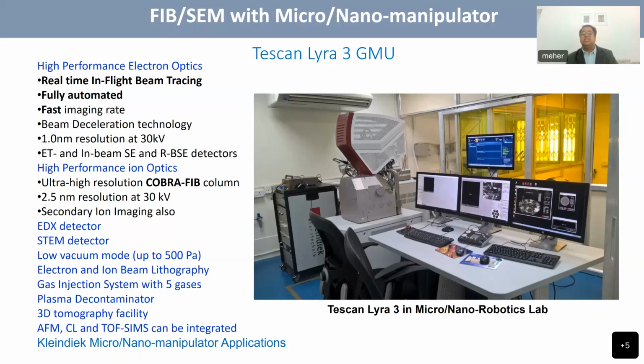because whenever we work with semiconducting nanoparticles, we use electrons for seeing those particles, and when we see the particles with the help of electrons, electrons also get deposited on the surface of these particles, and the electrostatic forces create too much problem in the process. So the process should be optimized very nicely. It takes some time, but we could do that, and people are also doing it, obviously. But here the idea was we were etching something from the fiber. The idea was, can we have very controlled structures on the tip of the fiber?